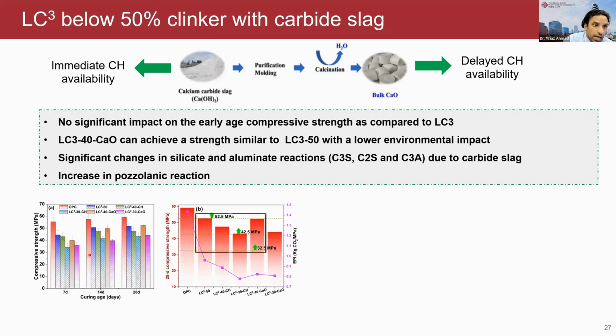The results were not as we expected, but again, very similar to the LC3-50, slightly lower, of course. But if you see at 28 days, the results are very comparable to the LC3-50, and we could further reduce the clinker content from LC3-50 to LC3-40.